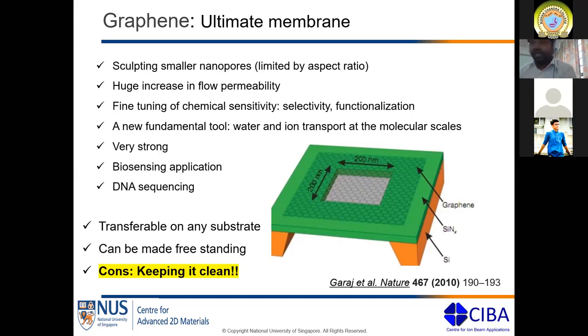However, the main challenge with graphene research, particularly from the membrane point of view, is to keep graphene clean, because whenever you expose graphene to the ambience, it absorbs moisture and the hydrocarbons present in the atmosphere, and it gets dirty. So to keep it clean, you need some specific process, and you have to optimize that process for this kind of application. What I mean by clean, you can see in a later slide.